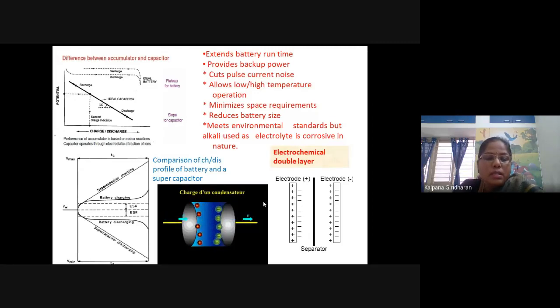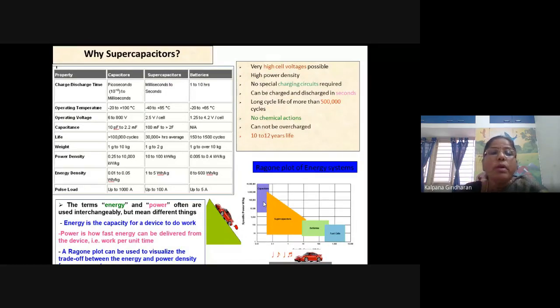Okay? And the left side graph shows the difference between the accumulator, the battery and the capacitor. The battery takes a longer time to charge and a longer time to discharge, whereas the supercapacitor can be charged and discharged even in seconds. So this is the double layer form. And the properties of supercapacitors lie between the capacitor and the battery. The operating temperature is minus 40 to 85 degrees Celsius, and the capacitance ranges from 100 millifarad to even 2 farads.